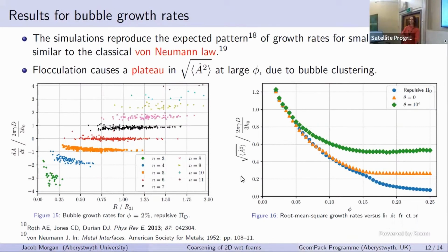But we know that the disjoining pressure must be positive, must be repulsive at equilibrium, and so there must be a little attractive component in order to balance it out. That's why you get adhesion at 0 contact angle with a finite film thickness.